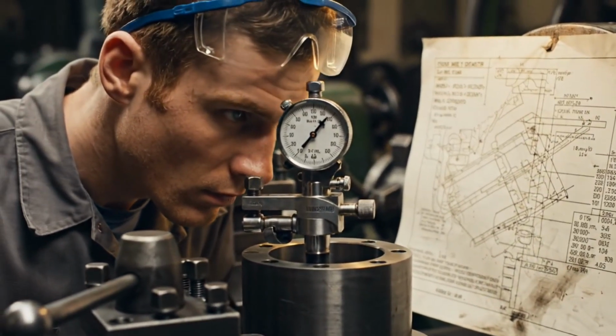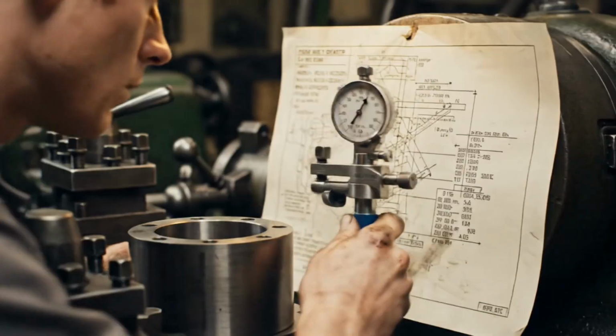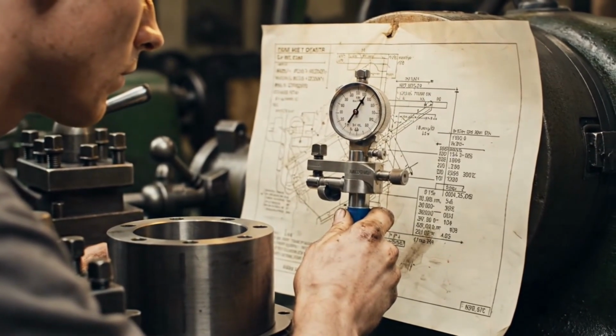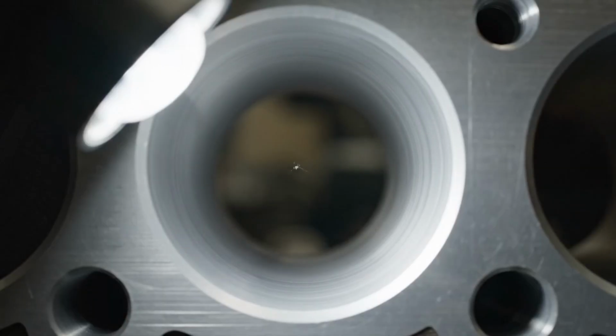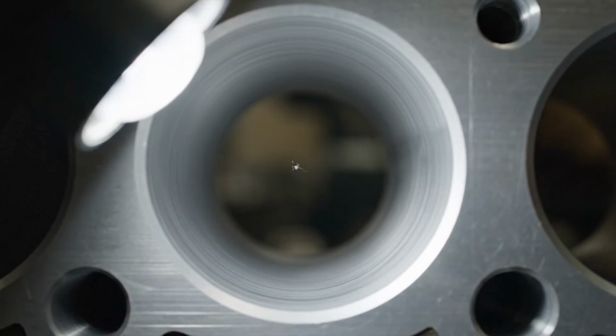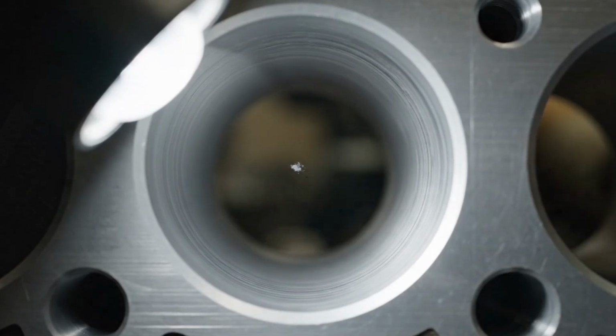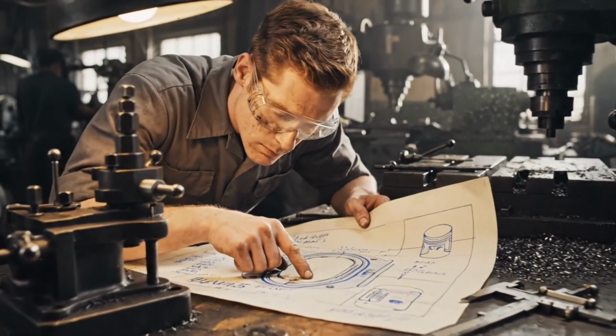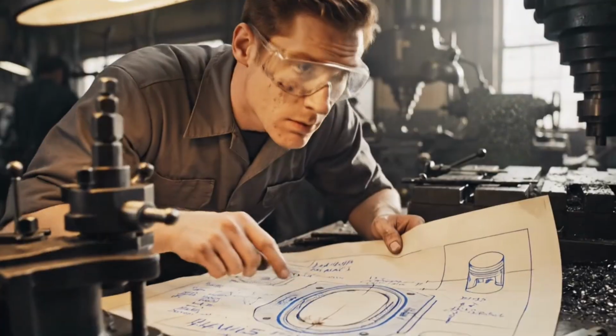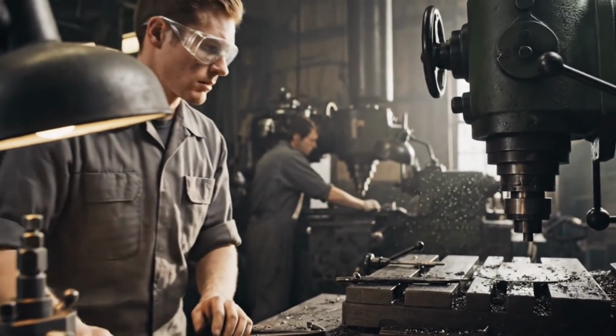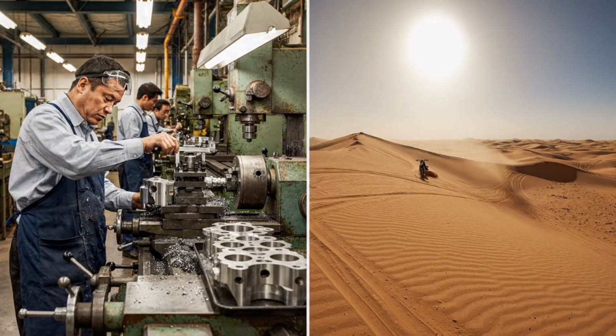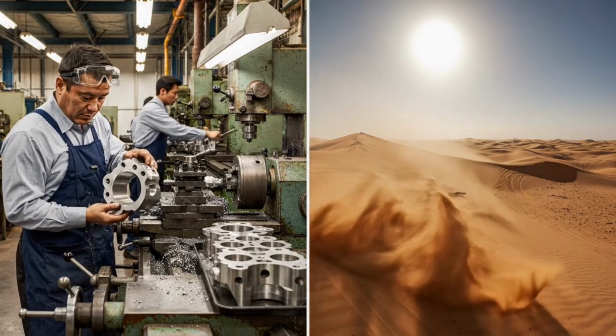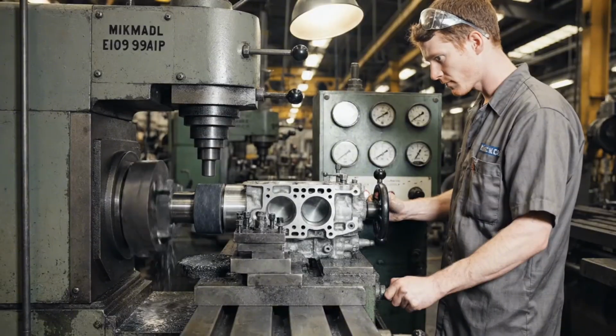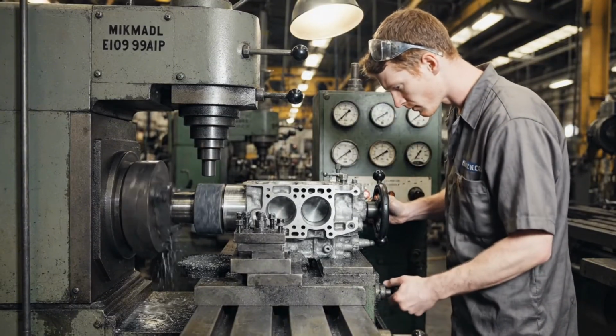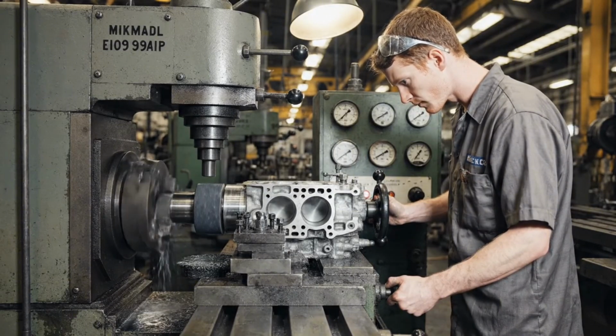The cylinder bores were the most critical features on the entire casting. Each bore had to be perfectly round, perfectly concentric, and cut to a diameter that was accurate to within fractions of a thousandth of an inch. A bore that was even slightly out of round would cause the piston to rock inside the cylinder, leading to uneven wear on the piston skirts and the cylinder walls. In a military motorcycle that might operate thousands of miles from the nearest repair facility, that kind of premature wear could mean the difference between a machine that kept running and one that seized dead in the desert.